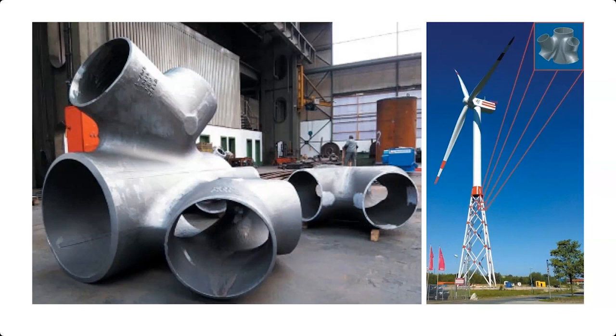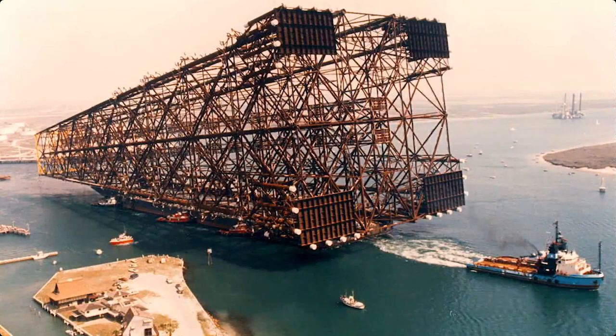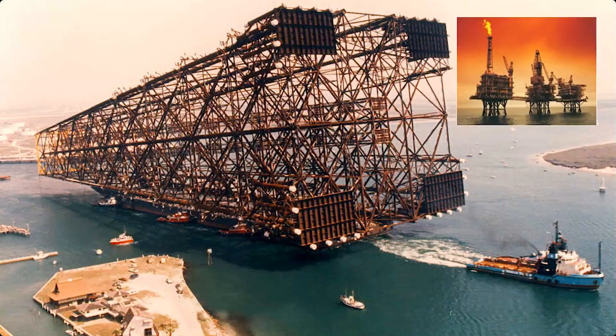So the offshore oil industry was using steel castings in these applications because if you think about what they're working on here, they have things like these giant towers that are holding offshore oil platforms that are constantly battered by wind and wave action. So that brings up fatigue considerations. They're also underwater in a very corrosive environment. So the amount to which they can limit the fact that the steel might start to corrode is going to be very important for a structure of this size. Having to maintain the connections is close to impossible. So the more durability that they can find there, both from the coating system and by minimizing the complexity or the propensity for the coating system to fail by making a much smoother joint, is going to be important.